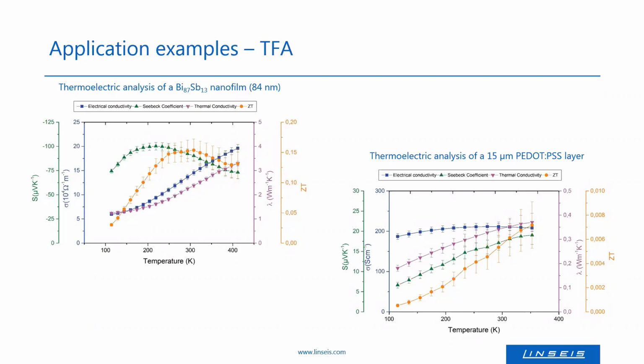On the right, one can see an analysis of a 15 micrometer thick PEDOT:PSS layer. PEDOT:PSS is a typical example for an organic conductor and thermoelectric material. Here again, a full analysis was performed, and the electrical conductivity, thermal conductivity, and the Seebeck coefficient were measured here in a similar temperature range from 110 Kelvin to 350 Kelvin. The sample here was prepared by drop casting, and one can see here then the resulting figure of merit in comparison to the bismuth antimonide sample. The values are much lower.